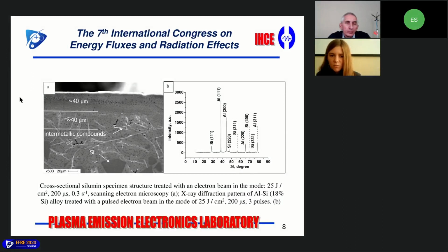When irradiating in the modes used, the silicon undergoes surface melting, dissolution of silicon particles and intermetallic compounds, mixing of elements in the melt via convection, and high-rate solidification with the formation of a submicro-nanocrystalline multi-phase structure composed of dendrite cells. So we can see a multi-layer structure. At this layer, we see that silicon and intermetallic compounds are melted, and in the next layer we see that aluminum and silicon are melted, but intermetallic compounds are present in this layer.